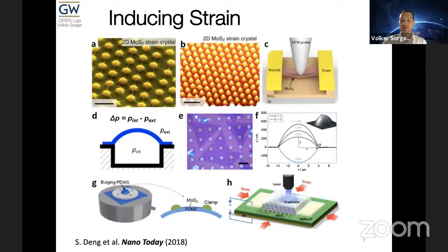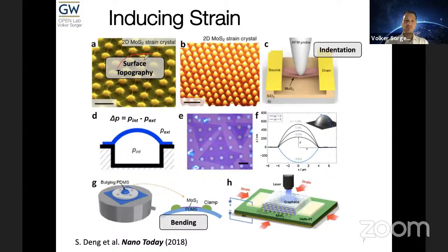What about 2D materials? Well, there are multiple ways we can strain them. For instance, we can add surface topography, we can add some sort of X structures, and we overlay this with 2D material. We can use indentation, we can bend the structure, sort of using PDMS, and then we can basically flex it and bend it.